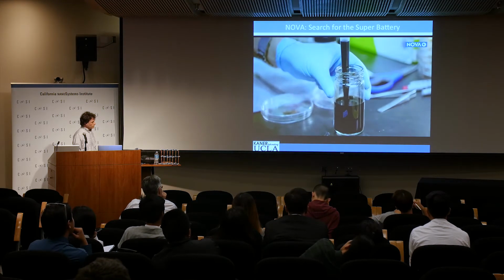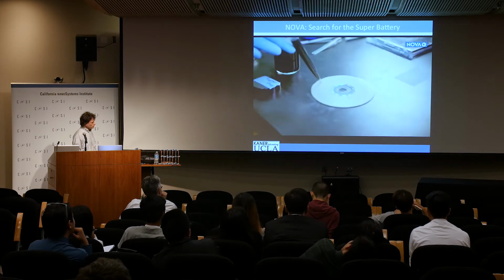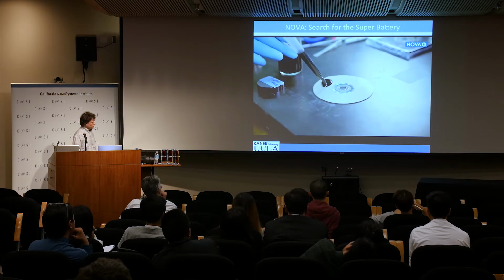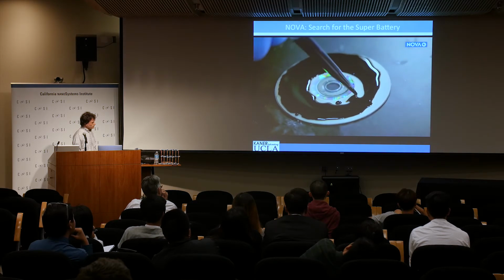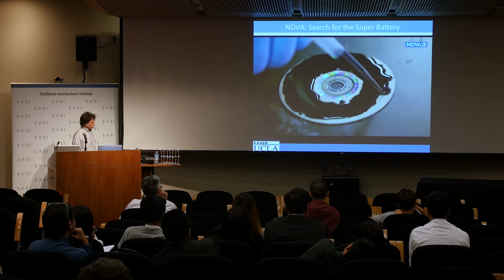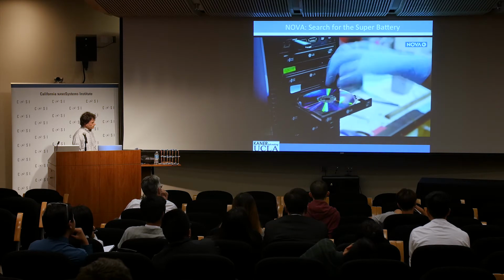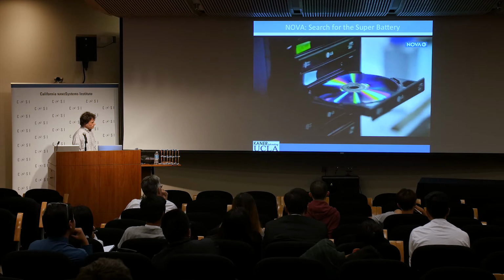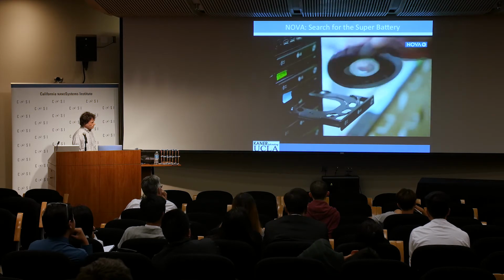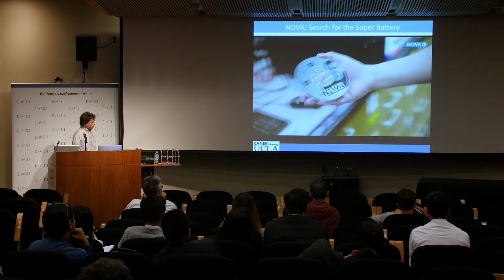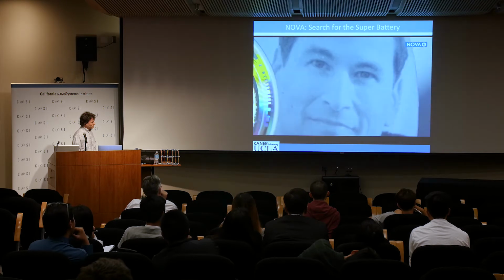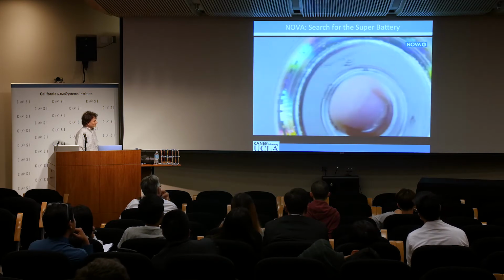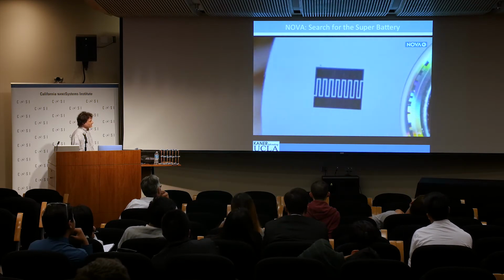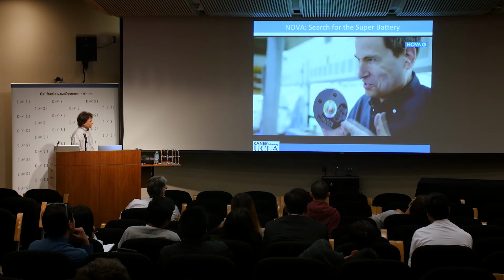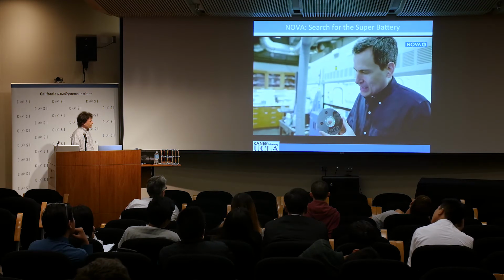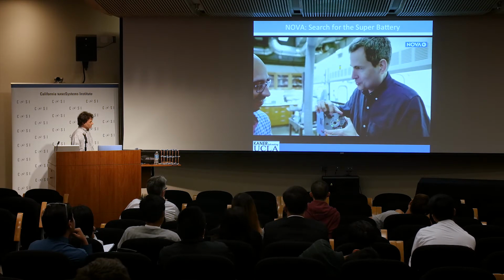Kaner's lab has developed a system to print exact designs. A layer of plastic gets coated onto the surface of a CD with a solution of graphite oxide. Once dry, it's inserted into a CD laser labeler. That's wild. But instead of doing its usual job of etching a label, wherever the laser hits the dried graphite oxide, that spot's transformed into graphene. Oh! I like this technology. Aside from a graphene likeness of David Pogue, El-Kady's printed 2 graphene electrodes. Obviously, there's a huge worldwide market for CDs with pictures of me in graphene, but I'm guessing that these are more important to the future of mankind.